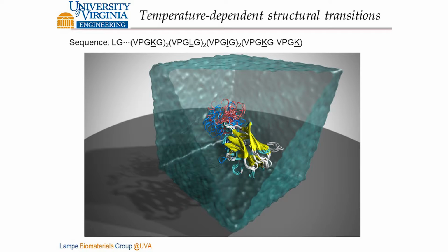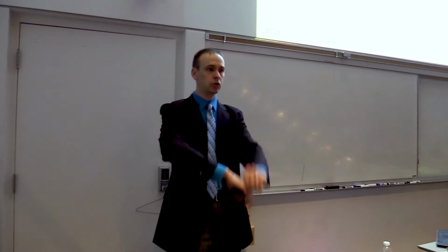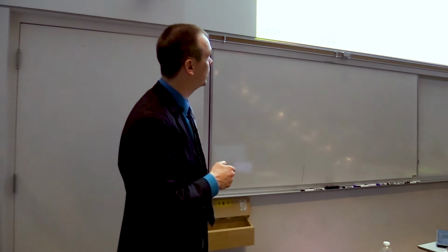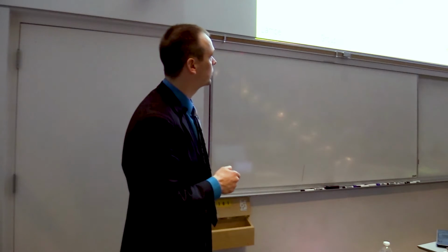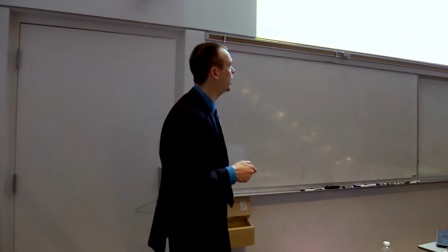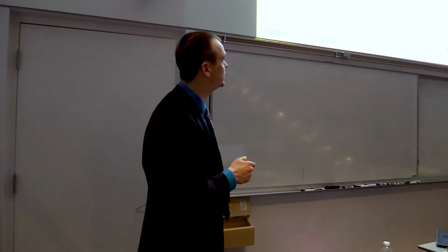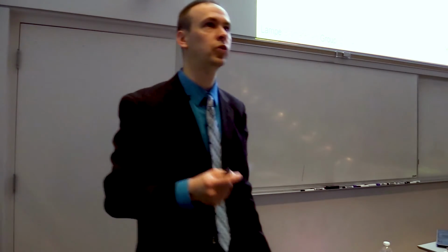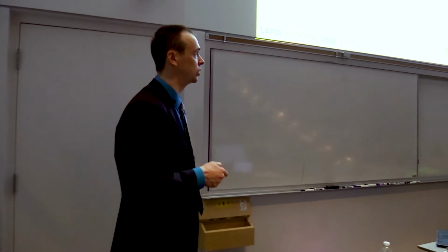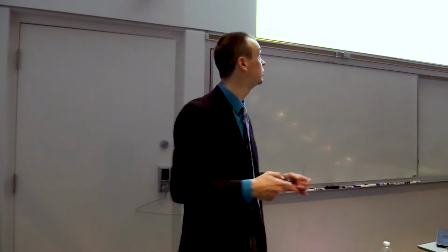And this laminin globular domain, you can see it's not really moving much, but this elastin-like protein domain is running around like crazy, super flexible. And you can see in some places some extended beta sheet showing up. So rather than just being random coil or alpha helix or beta turn, we see this show up, and it's pretty persistent. And that, we think, is super important for the self-assembly aspect of this material. If you can get organized structure, which a beta sheet structure inherently is, we think we can get things to kind of stick to each other and self-assemble.